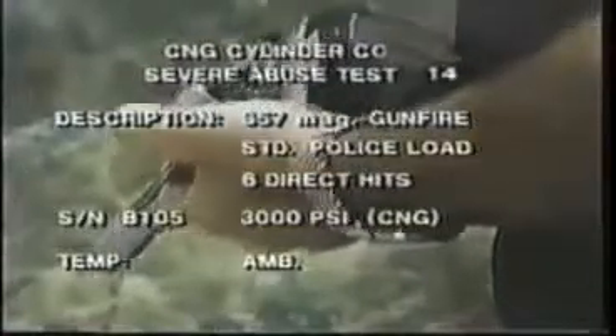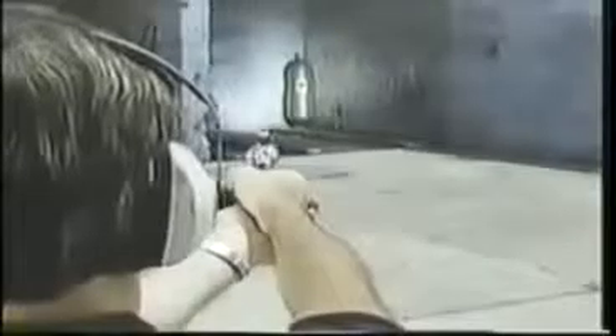The distance from the firearm to the cylinder was approximately 25 feet. There was no severe damage to the cylinder, other than damage to the composite matrix. There was no penetration of the metal, and even after this test, the cylinder performed well within its design limits. The cylinder exceeded the minimum burst pressure of 7,500 psi. All cylinders were charged with natural gas.